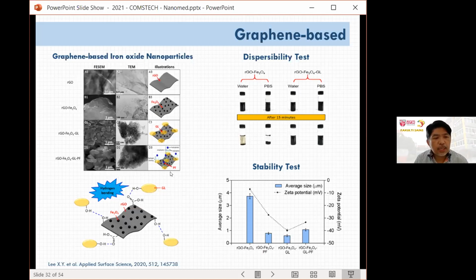In this work, we use Ganoderma lucidum extract, which is able to stabilize the RGO, the reduced graphene oxide, iron oxide via hydrogen bonding. One of the big issues when we work with graphene is high toxicity, so we also use Pluronic F127 to reduce the overall toxicity. Other than that, the best thing when you use the polysaccharide is that the hydroxyl functional groups on this polysaccharide exhibit hydrophilic property, and then the dispersibility and also the stabilization were enhanced tremendously. If you can see from here, after 15 minutes the dispersibility is still very good, but without the GL, you can see the deposition or sedimentation of the iron oxide after 15 minutes.